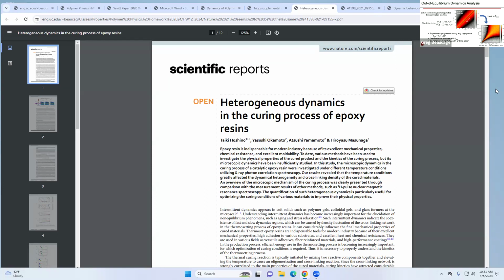So yeah, these experiments are very difficult because you have to play around and fiddle with the acquisition parameters so that you can get these figures to show up over a relevant time domain. And it all depends on your material, right? Who knows if you have something that's relaxing fast or slow. These ones are really tough to capture because they're changing so drastically, right? This is relaxing very fast. And that's basically the curing process there. What we saw was that the relaxation time slowed down a lot, orders of magnitude. So we had to be really careful about our design of experiment, how we were able to capture that time scale.